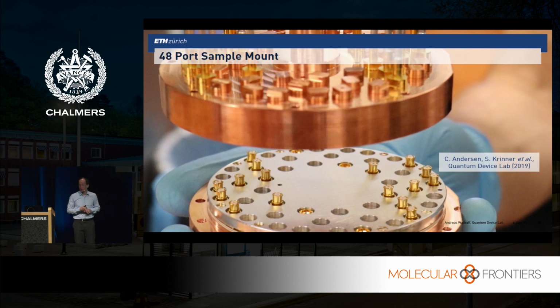this chip then, to operate properly, it's a superconducting chip. So first it has to be cooled down to temperatures that are way below the transition temperature of the superconducting material. So that's, in our case, for the two materials that we use, niobium and aluminum, either around 10 Kelvin above the absolute zero of temperature, or about 1 Kelvin above the absolute zero of temperature. And so therefore you need to put these chips into a cryostat.